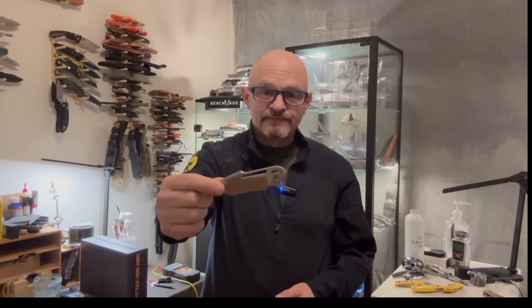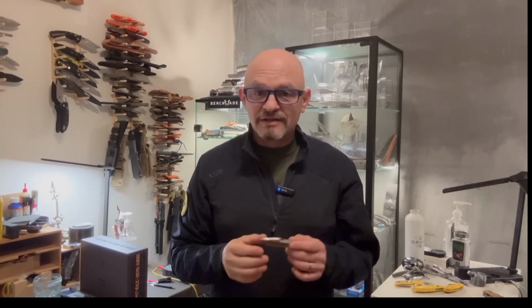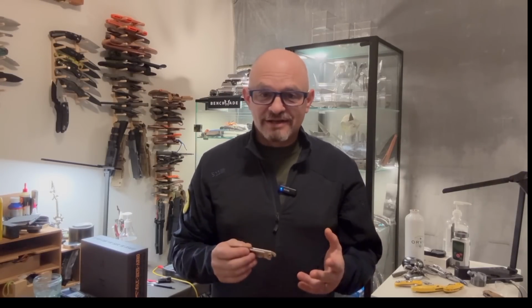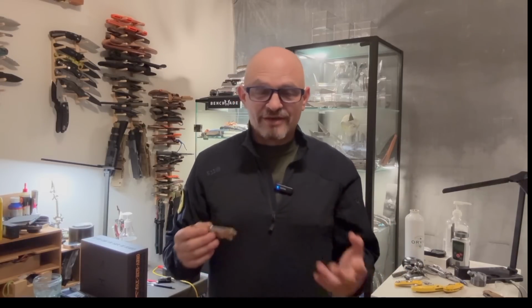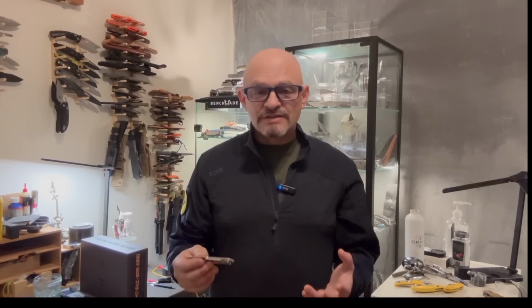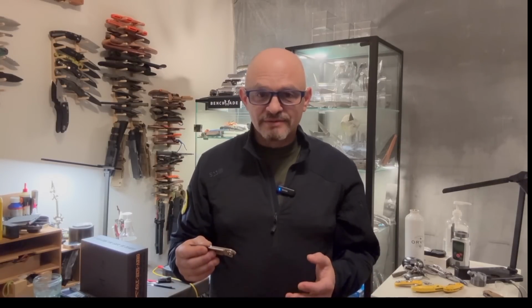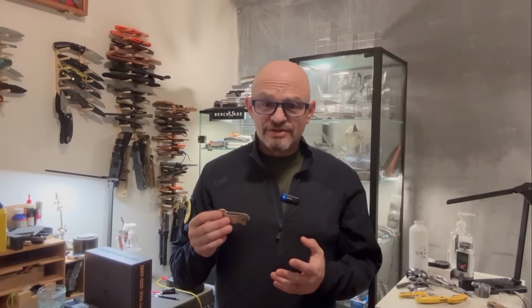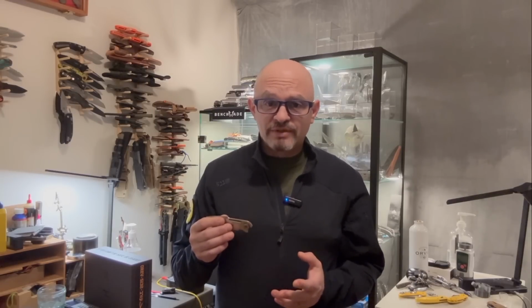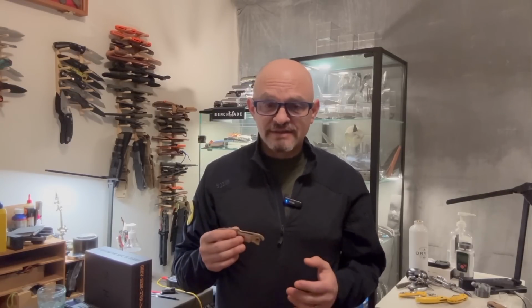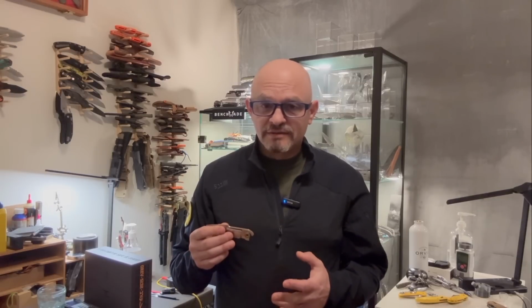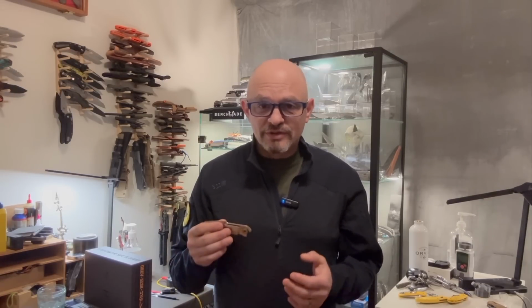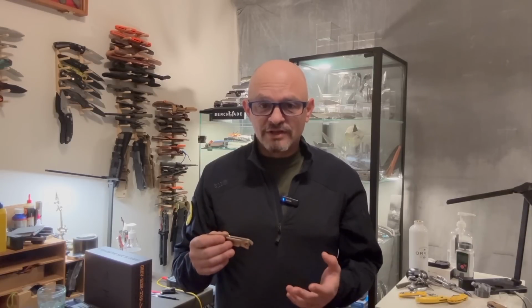Going forward, I'd like to remind you that every time I measure a blade here, it is just one blade, one, out of many that were produced. Every batch has a high end and a low end in every dimension of measurement. That's why my disclaimer remains. The methods I used in this video are not industry standard. The industry standard method is to test a minimum of 5 blades for a batch of 150 or less. And then it jumps to 20 to do it correctly in accordance with acceptable industrial quality standards.